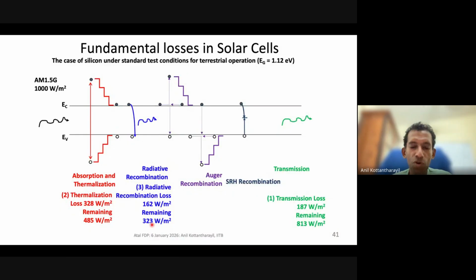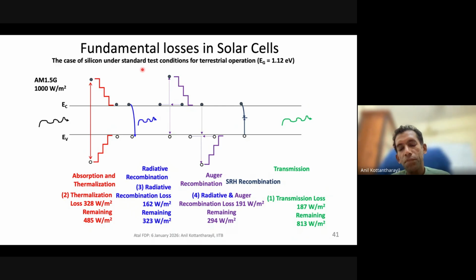So what is remaining is 32.3%. But if you now consider Auger recombination also, both radiative and Auger together, you would lose about 191 watt per meter square. So what you have remaining is 294. So 294 out of 1000, so 29.4%, is the theoretical maximum efficiency of silicon solar cells. That means 70.6% is just lost to these mechanisms. Now, this is under ideal conditions, so you need to design a solar cell carefully to actually bring the efficiency close to this number.